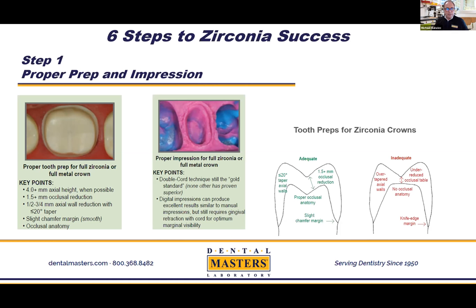Now, this is true really for just about anything we do in dentistry, but particularly true for glass ceramics and oxide ceramics, meaning zirconia. We would really like to see the following whenever possible: 4 millimeter axial height, 1.5 millimeter occlusal reduction. We want 0.5 millimeter to 0.75 millimeter axial wall reduction. And we certainly don't want that tooth to be over tapered. We'll lose retention and resistance form.